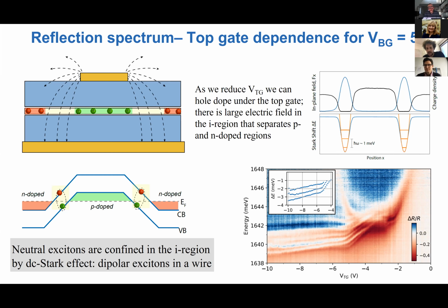Yeah, so this one, I think it would contribute to enhancement of interactions, but we haven't estimated how dramatic it would be. Basically, the size of the dipole would still not be terribly large. Roughly what we know from dipolar excitons in gallium arsenide is that if the dipole size is comparable to the Bohr radius, then you get about a factor of 5 to 10 enhancement. So it would contribute, but I don't know if it will be 10% or a factor of 5. Honestly, I don't know the numbers. But I think that the overlap arguments should already put us in, and given the line widths, should give us some degree of anti-bunching. But maybe I'm being too optimistic.